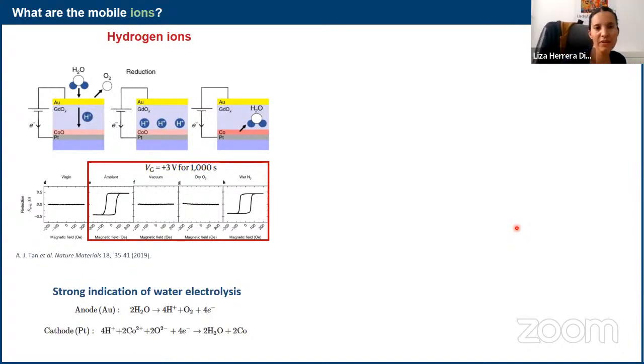And what is important about this is that something that is very accepted by now, for the oxygen as well, is that there is a very important interaction with the water from the atmosphere. So they made it very clear here that there's a strong influence of the water, because here they need the water to dissociate at the interface to get these protons inside. So it depends a lot on the humidity of the atmosphere.